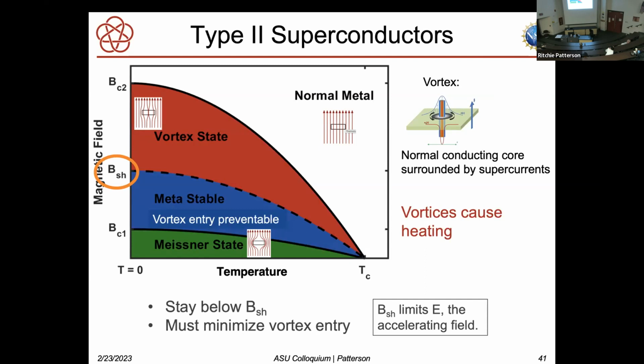We need to keep the magnetic field below this superheating critical field here so that we don't enter the vortex state. So the main goals are to stay there and to minimize vortex entry. And I should say, the reason this superheating critical field matters is because the electric field that you sustain in the cavity is proportional to the magnetic field. So if there's a limit to the magnetic field, there's also a limit to the electric field. But the electric field is the thing that's doing the accelerating. So you would like that to be large, but you're limited by the superheating critical field here.